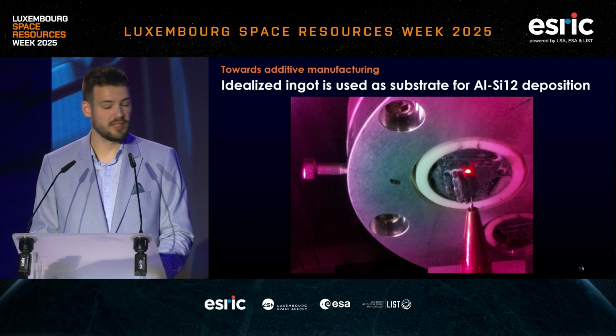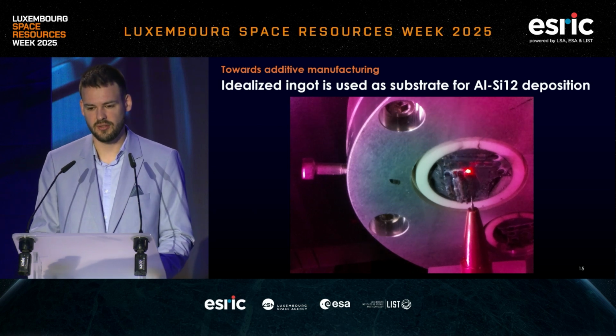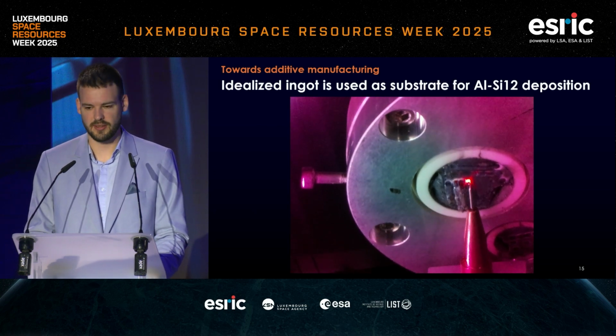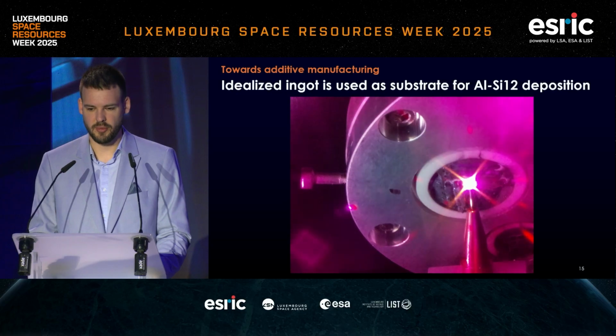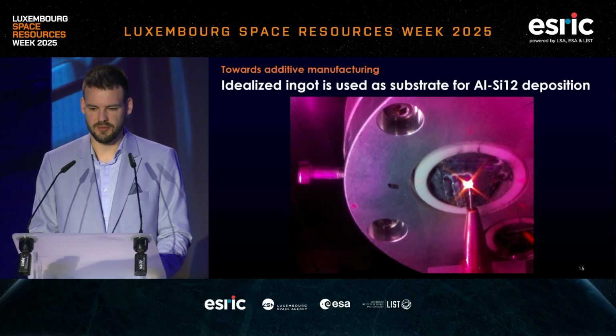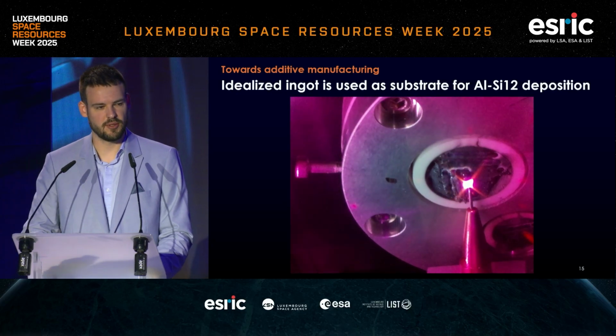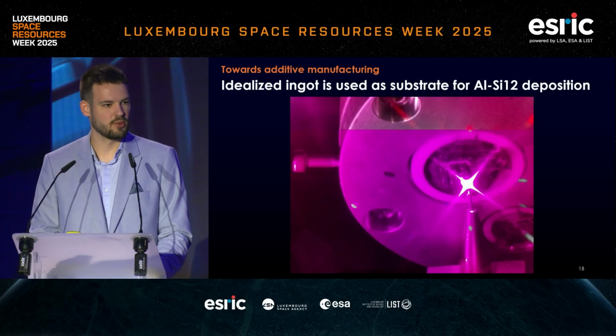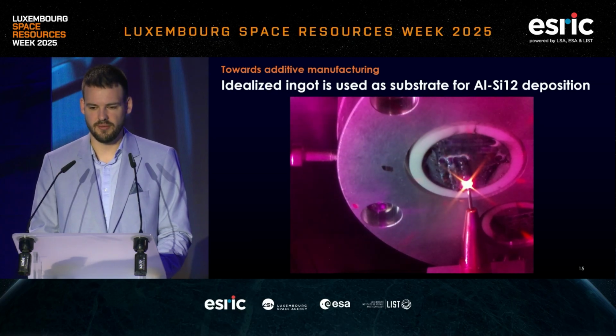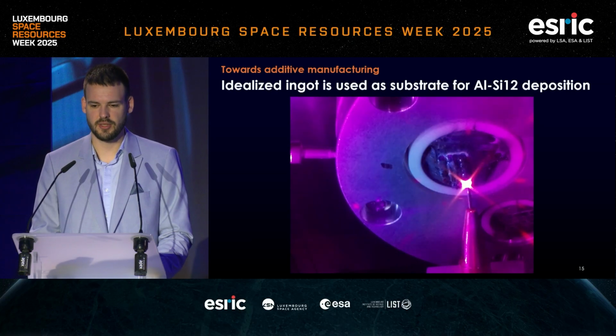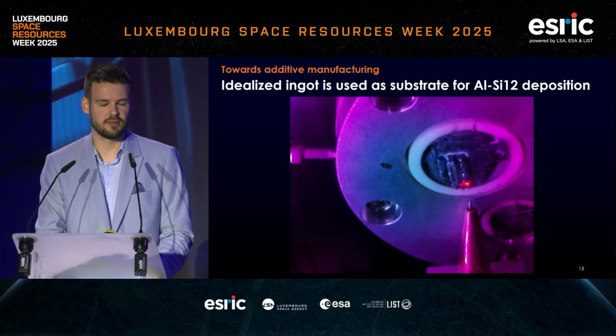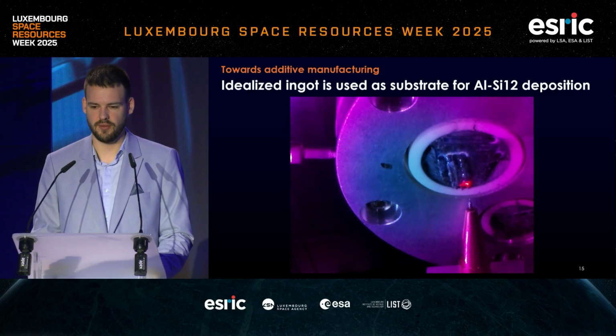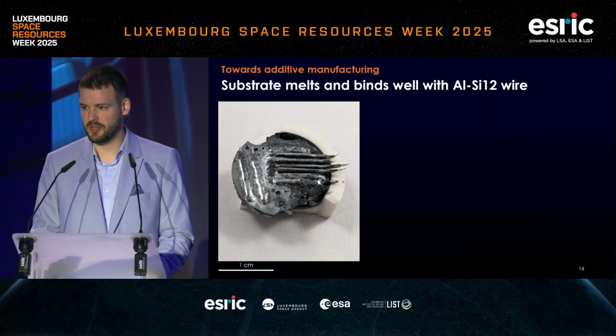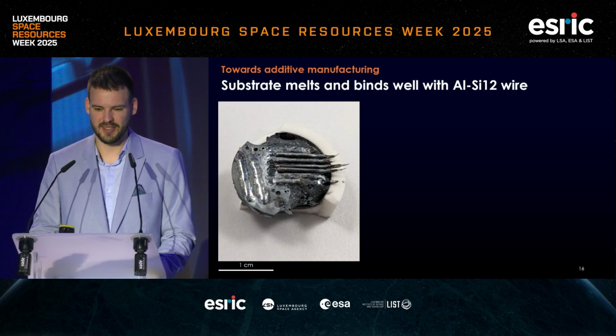And I have a video about the deposition, what this deposition process looks like. So here we can see we're forming a melt pool and then slowly feeding the wire in it, and here it's just a first layer. The main thing to observe here is we get a very nice melting of the substrate and a kind of very nice weld bead in a way deposited on it. If we look at the kind of samples we obtained, again, that's kind of the first sample we got. So obviously there's room for improvement.